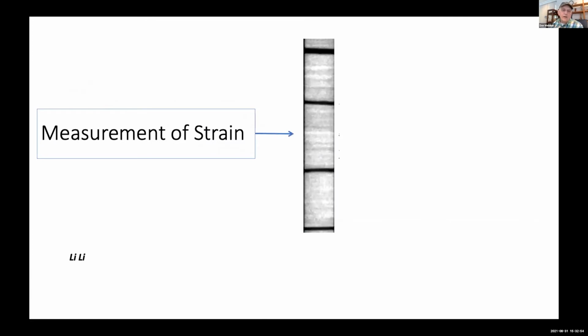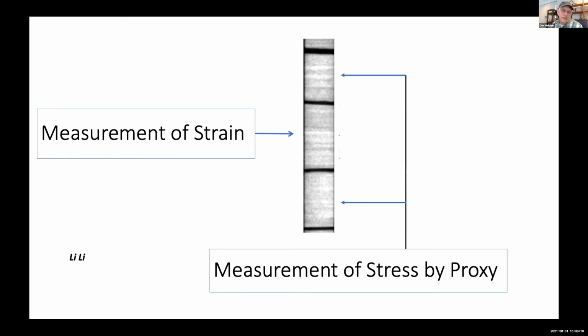And so for measurement of strain, we do simple things. We put a metal foil in the sample stack. And so you can have 3 samples stacked on top of each other, or more or less. And you just take pictures and measure the length of this as it evolves. You can use top and bottom samples that are some standard you have, like corundum, and the middle one being the sample. So you can compare the strain fields of the sample and of the reference. This is very convenient